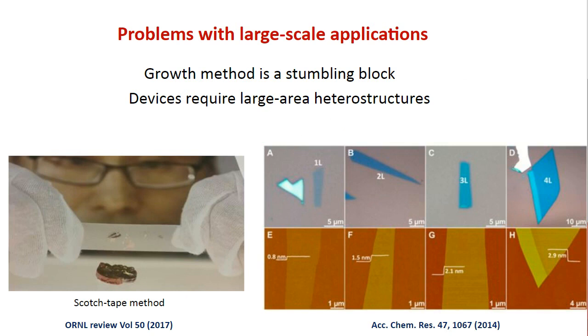Now, as I was mentioning, when graphene and other TMD materials were discovered, they were not discovered by any thin film growth method. They were discovered by what is called the Scotch tape method. Essentially, you take a Scotch tape and peel away layers of the material. So you take a single crystal, put a Scotch tape on it, and you peel out as much material as you can, and then hope for the best, literally, because whatever you peel out could be 10 layers, could be 20, but could be 1, 2, or 3.